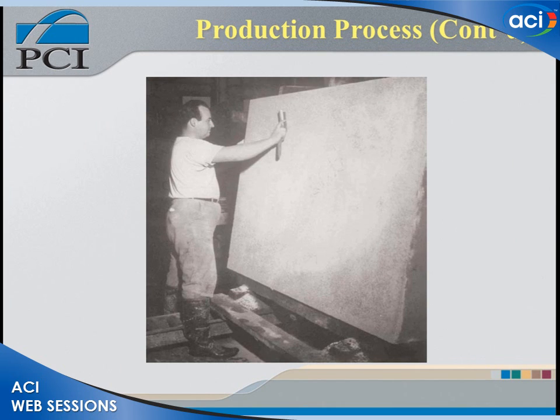As soon as the panel was removed from the mold, it was stacked in a vertical position on a traveling easel and gone over with an electrically driven belt sander to remove excess mortar on the face, and then wire brush to remove the surface mortar and expose the aggregate in their true colors. Each panel was then checked for size, broken edges, sand pockets, and repaired if necessary. Repairs were made within 36 hours of casting.